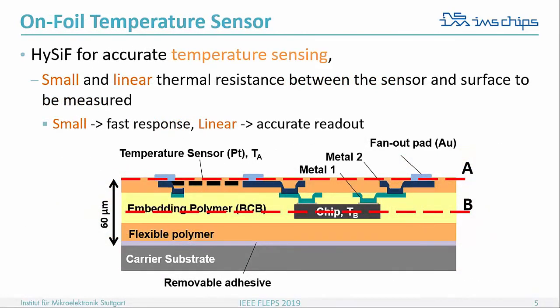Okay, so in order to have this system for temperature sensing, we have already well-established silicon technology and silicon chips for very accurate temperature sensing. However, if you use such chips in this packaging, you will get a very long path and very high thermal resistance between the surface of the chip and the surface to be measured. And that will lead to inaccurate or very slow measurement or response time of the sensor on the chip.